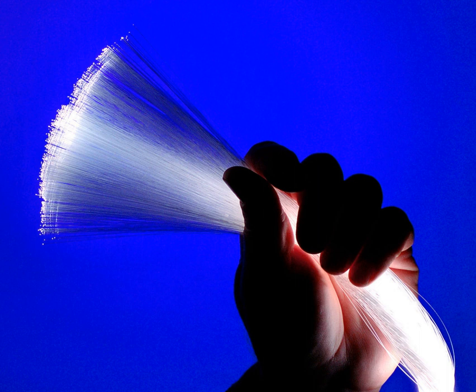In crystalline materials such as metals and ceramics, in addition to pores, most of the internal surfaces or interfaces are in the form of grain boundaries that separate tiny regions of crystalline order. It has recently been shown that when the size of the scattering center, or grain boundary, is reduced below the size of the wavelength of the light being scattered, the scattering no longer occurs to any significant extent. This phenomenon has given rise to the production of transparent ceramic materials. Similarly, the scattering of light in optical quality glass fiber is caused by molecular level irregularities in the glass structure. Indeed, one emerging school of thought is that a glass is simply the limiting case of a polycrystalline solid. Within this framework, domains, exhibiting various degrees of short-range order become the building blocks of both metals and alloys, as well as glasses and ceramics. Distributed both between and within these domains are microstructural defects that provide the most ideal locations for light scattering. This same phenomenon is seen as one of the limiting factors in the transparency of IR missile domes. At high optical powers, scattering can also be caused by nonlinear optical processes in the fiber.